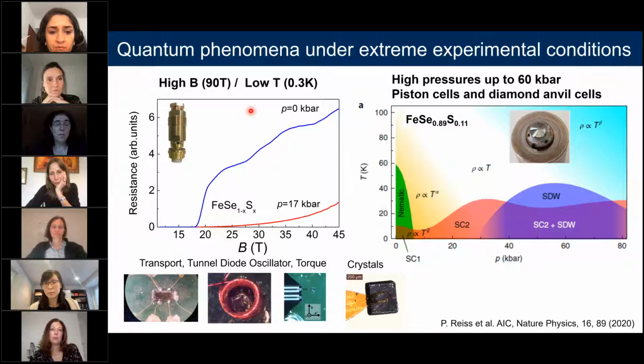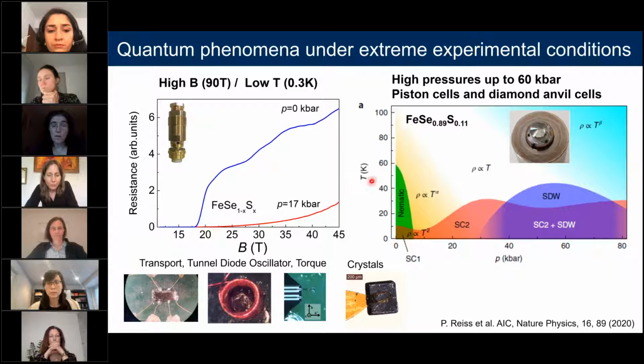Another type of experiment that we do in our research uses extreme conditions of high magnetic fields and high pressure to tune the different competing interactions. For example, in the phase diagram on the right, we can tune, with a single sample inside a pressure cell, a piston cell, between nematic, superconducting, and spin density wave phases. And we can explore, using quantum oscillations, the behavior of electrons in different phases. We use a large range of techniques, from transport studies, tunnel diode oscillator studies, and torque measurements, and we rely on having extremely high quality single crystals for this quantum phenomena to be observed.